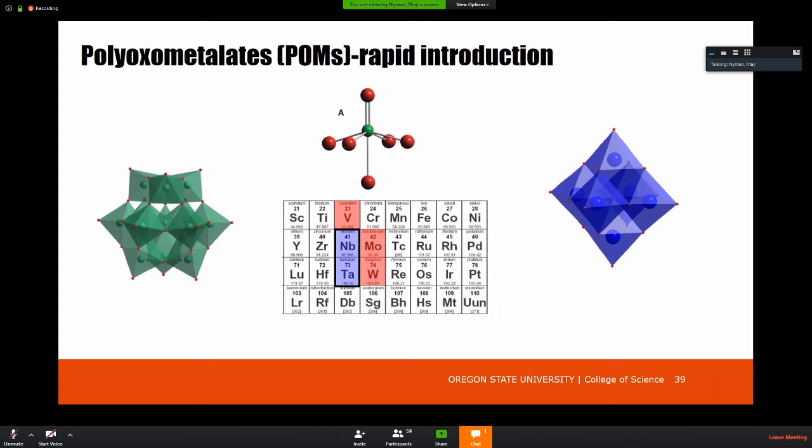So after 3 days with cesium, rubidium, potassium, your decaniobate is completely gone. But your sodium, or your lithium and your sodium solution, is still converting. Okay, so this is indeed dependent on the alkalis. Here we are monitoring the disappearance of that decaniobate fingerprint peak with lithium, potassium, cesium, at 3 different concentrations.